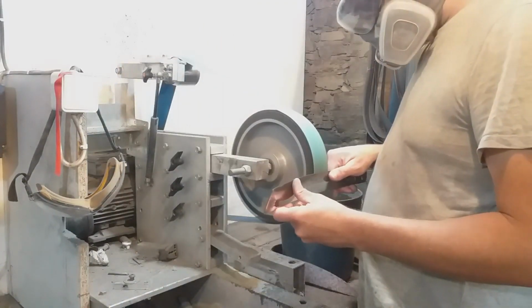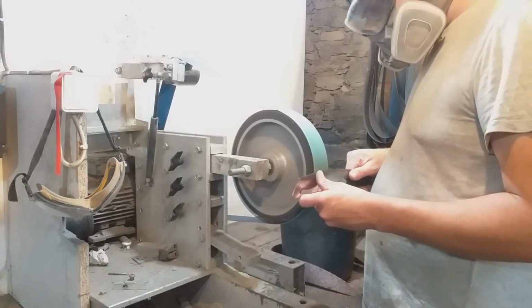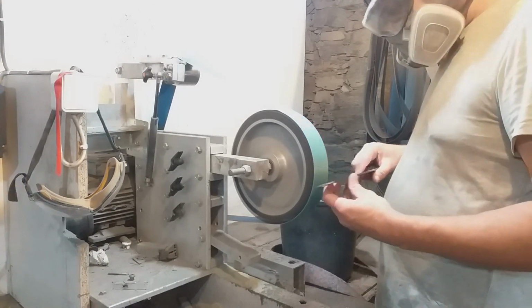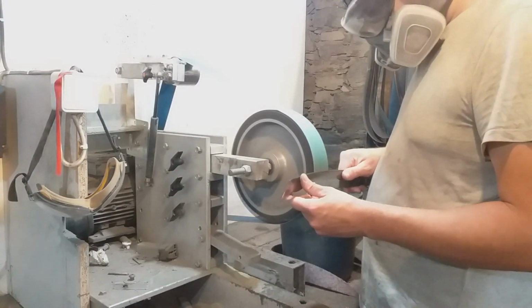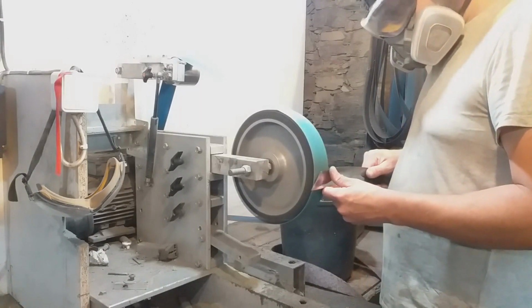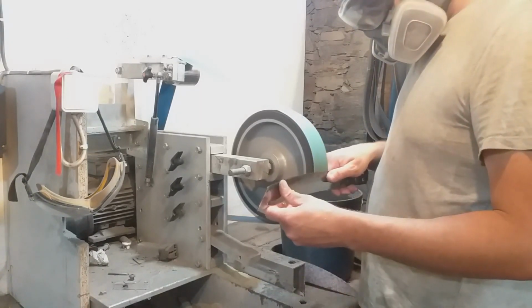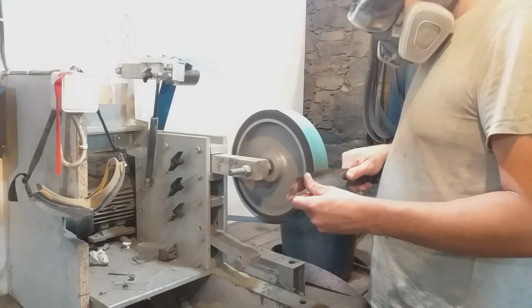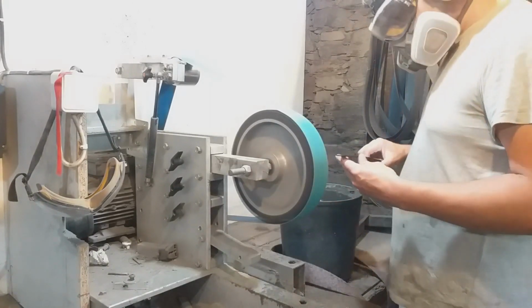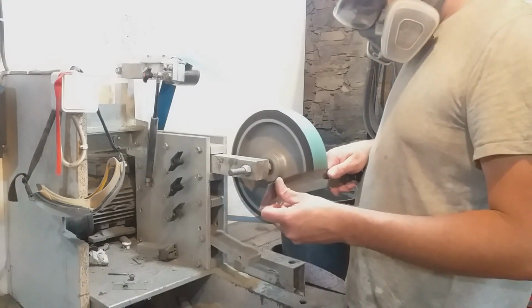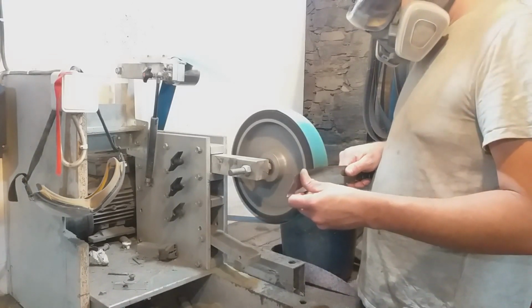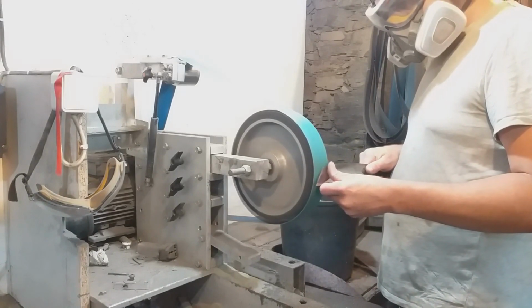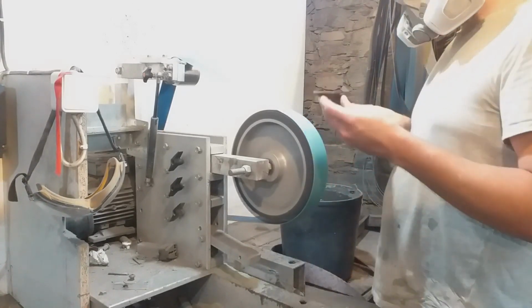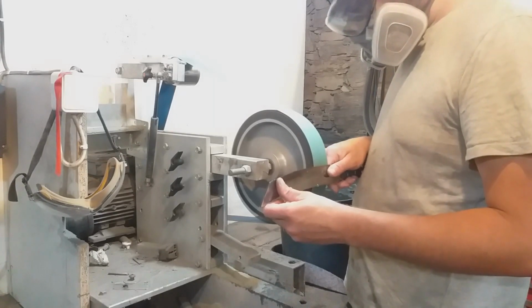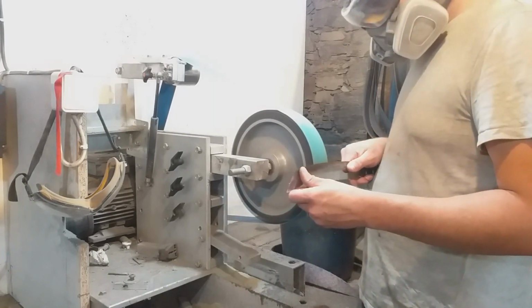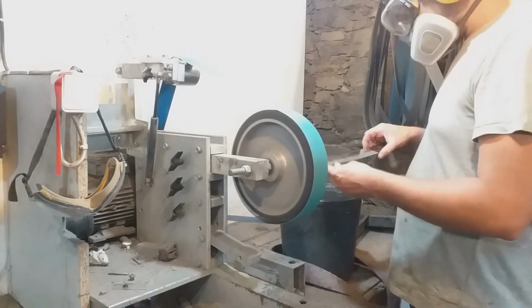It's then back onto the grinding wheel to finish the hollow grind. This again is a particularly tedious process because you must ensure that the blade does not get hot above the tempering cycle temperature. For example, there's a thing with knife making where they say if you couldn't hold that piece of steel to your lips without getting burnt, that it's too hot, which can happen very quickly. So it's always a case of using a brand new fresh ceramic belt in order to cut through the hardened steel, and again take off a few microns per pass, spend a couple of hours and make sure the blade never gets hot.